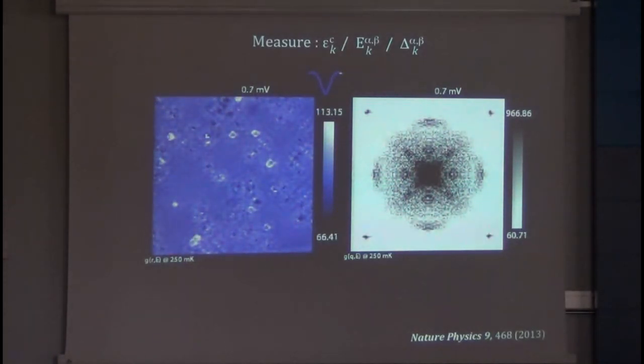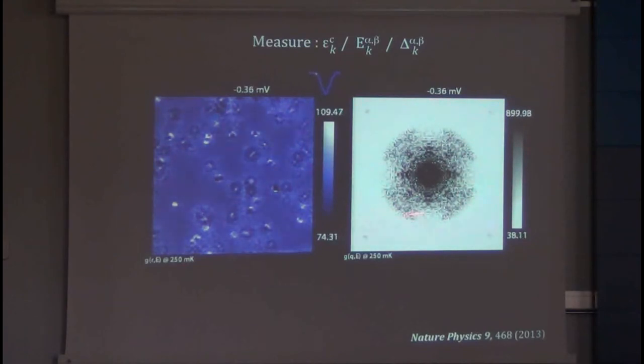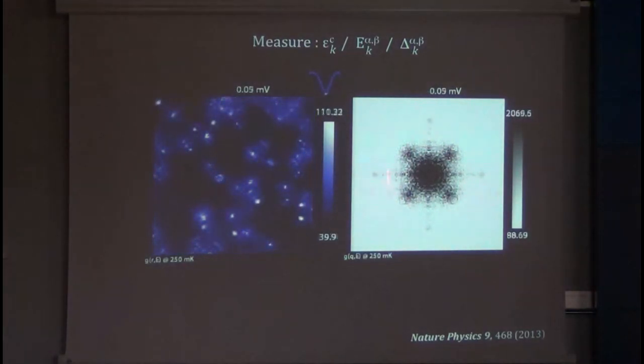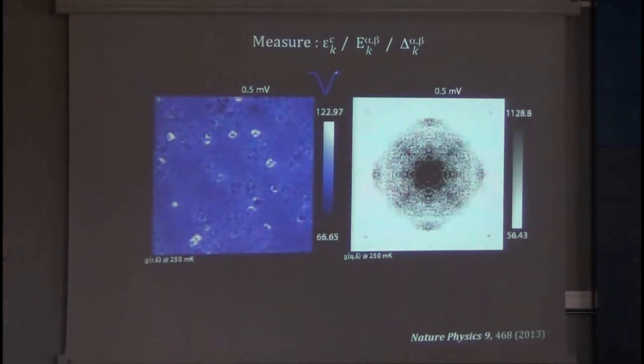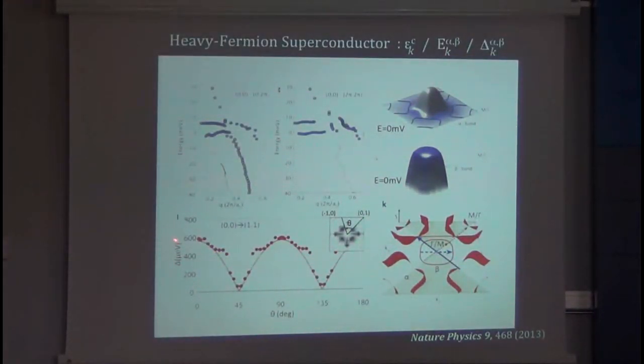We can tell because there's a whole bunch of scattering at zero energy with a particular symmetry. And from all the details of this very rapid evolution of momentum space structure of the Bogoliubov quasiparticles, we were able to extract, first of all, the angle dependence of the energy gap directly in momentum space. And secondly, the details of what the cerium cobalt indium 5 energy gap structure looks like, with precision in the 10 microvolt range and throughout momentum space. Some of the referees for this paper felt that this was impossible. But I guarantee you, it's correct.